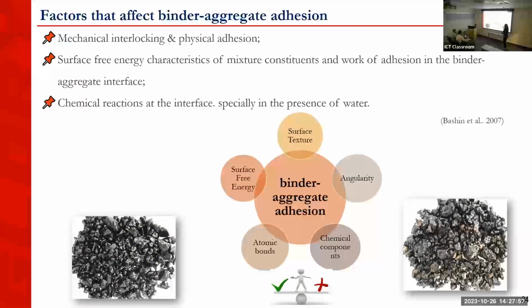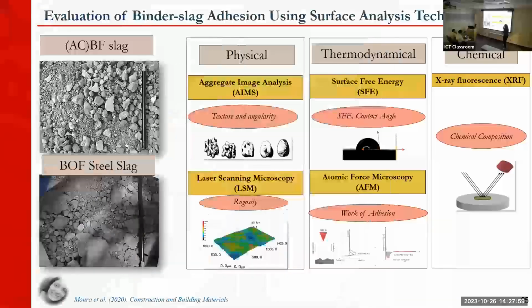To evaluate the binder aggregate adhesion, we evaluated physical adhesion using AIMS and laser scanning microscopy. AIMS to check texture and angularity differences between those two slags. Laser scanning microscopy to check rugosity of the materials. Those things can contribute to the physical adhesion.